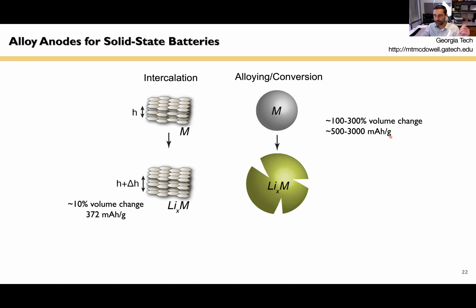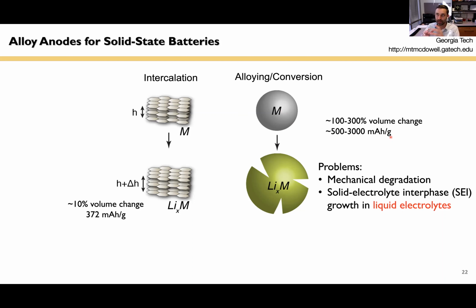So these have been studied for decades. We've known about them for a long time, and they're currently being commercialized for conventional lithium-ion batteries with liquid electrolytes. It's been very challenging, though, because these big volume changes during charge and discharge, the volume changes of the particles inside the battery, cause mechanical fracture and continued growth and contraction of the surfaces, which exacerbates side reactions in liquid electrolytes in particular. Going back to the very beginning of this talk, because liquids can wet surfaces regardless of how they change, you grow what's called the solid electrolyte interphase on the surface of these alloy anode materials. And every time you expand and contract your alloy anode, you form new surface films.